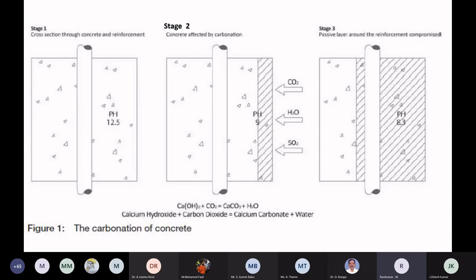So the pH value keeps on reducing from 13, and when it reaches less than 9, corrosion starts. Then the steel bar will get affected very quickly. Once the rebars are affected, your area of rebar or steel will get reduced. Then you will get failures. So it is always essential to protect your concrete from the environmental effect, as illustrated in this picture, by maintaining a uniform cover. The cover has to be ensured by the engineer in charge at the site. That means adequate cover blocks at adequate locations have to be ensured before concreting takes place.